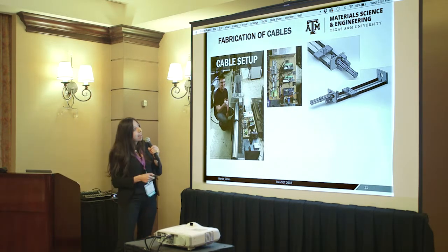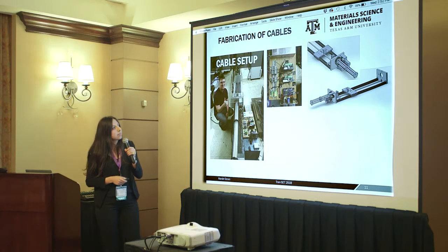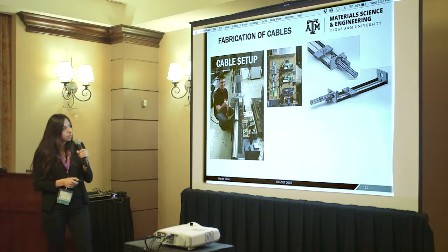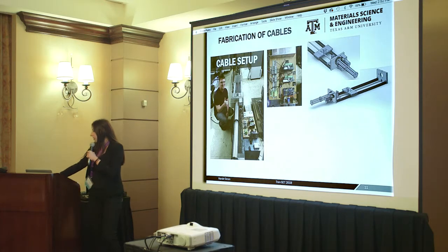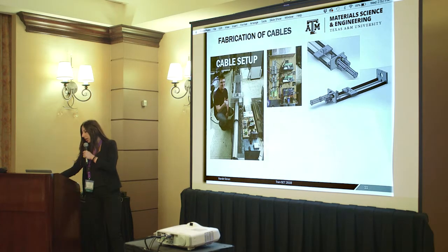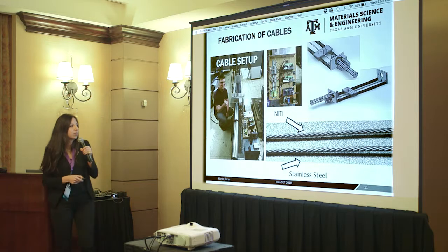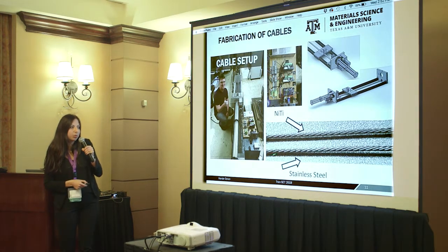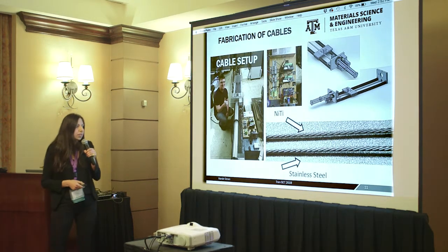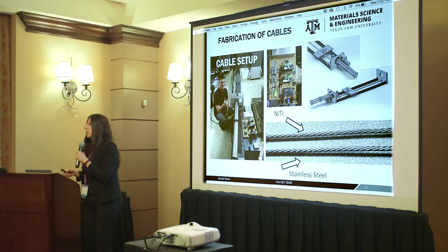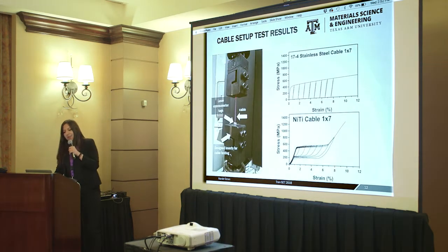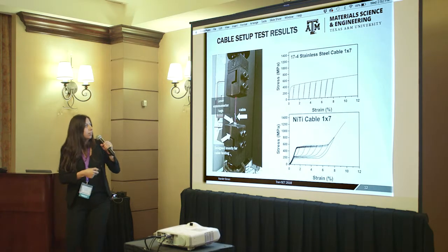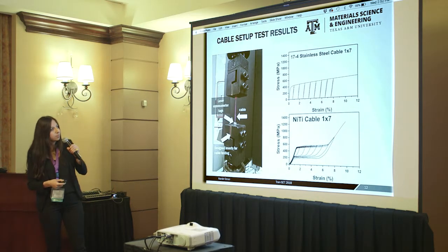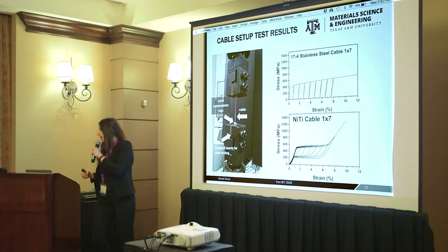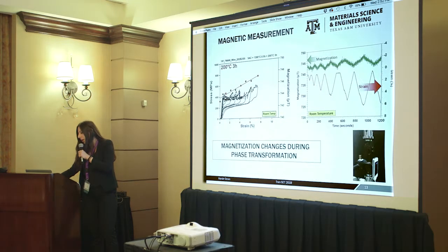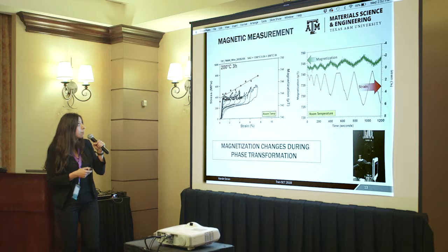So this is our cable setup, and he built this control system and designed it in SolidWorks, of course, at the beginning. As a result, we can now produce these cables in our lab, in nickel, titanium, and stainless steel. It's 1 by 7, all right? Afterwards, we tested these cables, and you can see the results. Again, we designed the grips for our projects.